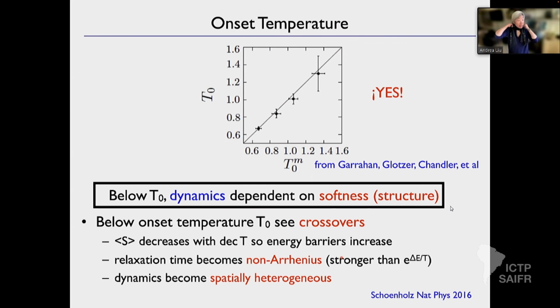And I think they could even define something like softness. I wasn't going to talk about this, but it turns out that we took particles with Hertzian repulsions and looked at plasticity, so we looked at quasi-static shear. This was work by Sean Rideout. We looked at it across dimensions, 3, 4, and 5 dimensions, and we trained on softness.